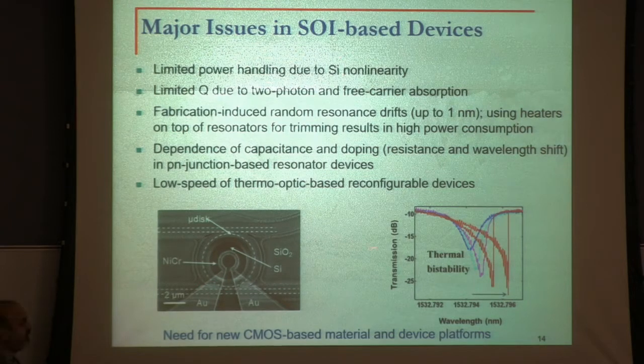Now, when you start cranking up the power, as shown here, originally you have a very nice resonance, the blue curve. But when power goes up, the heat generation and the free carrier loss start to compete. And then at some point, you will see that your resonance has a bistable behavior. That's just the problem of high power that silicon cannot handle.